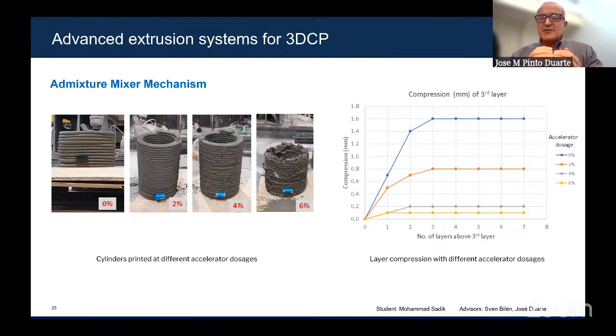Obviously, the research that we develop in this case is to define the right amount of admixture to be injected before extrusion. If it's too much, it will set too fast and clog the machine, or you get, as you can see in these images on the right-hand side, not a very good printing quality. So in this case, for this type of mixture and for the type of admixture that we were using, 2% was the ideal amount of admixture to add to the nozzle.